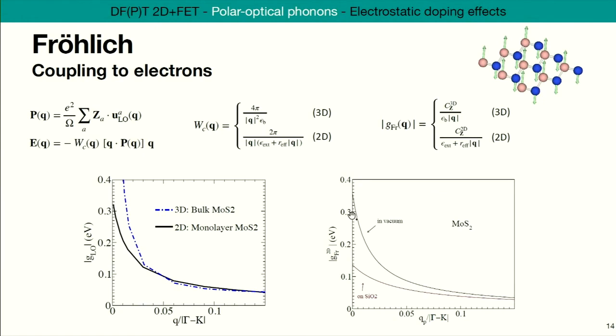Okay, and here again, we can look at what happens when you change the environment to look at how this screening works. And indeed, we see this very characteristic thing that in the long wavelength limit, screening comes from the environment. And so if you put MoS2 either in vacuum or on SiO2, you get very different values of the coupling at small momenta.